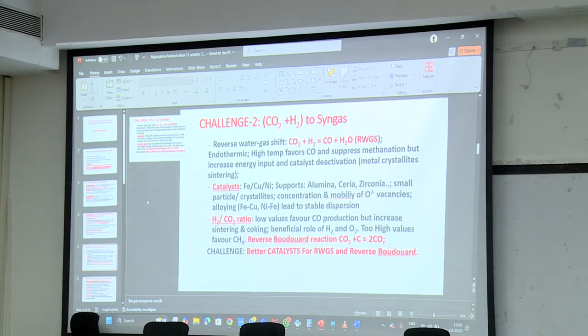This is an endothermic reaction. High temperature favors CO and suppresses methanation, but increases energy input and catalyst deactivation. Catalyst deactivation occurs by two pathways. One is metal crystallite sintering, the other is coke. CO is favored by high temperature. At low temperature, methanation is more favored. So you have to strike a balance. Aging, coking, and metal sintering are all higher at high temperature, where you have high selectivity for carbon monoxide. So it's a question of balancing between different parameters.